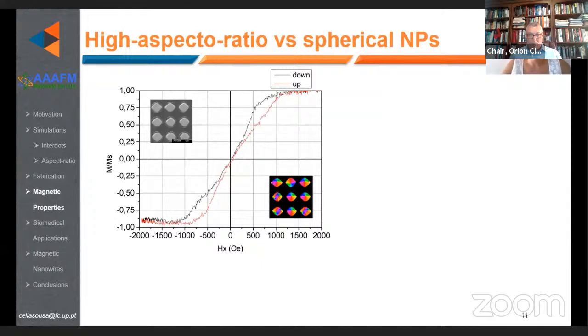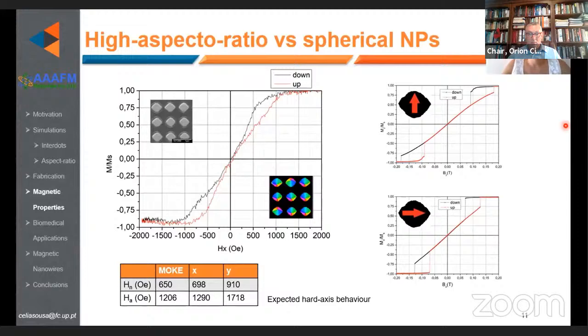and the 50 nanometers thick iron layer is the active magnetic layer. Magnetic hysteresis loops measured in the prepared samples after the liftoff process clearly show the vortex state in iron nanodiscs with around 500 nanometers in diameter and 50 nanometers thick. Zero remanence is observed, and the annihilation and the nucleation fields were determined and are in good agreement with the micromagnetic simulations in the X direction.